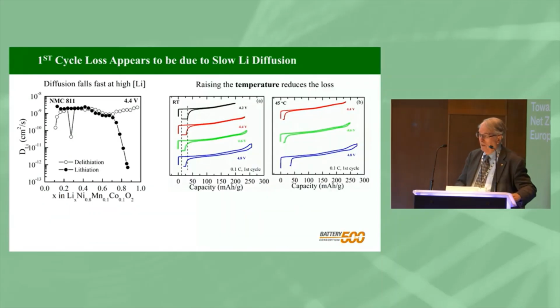So what we found out, this is a diffusion control process. It's not clear yet whether it's in the bulk of the materials or in the surface of the materials. But if you look at the solid circles here, this is the diffusion coefficient, lithium going in, and you can see this falls off the cliff at about 80% lithium content. So this is a vacancy diffusion mechanism, and in fact you need 2 vacancies next to each other for the lithium ions to diffuse. So it gets more and more difficult as you fill the lithium up.